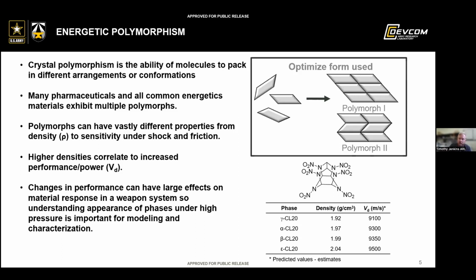So this is an example where we can use high pressure to understand how this material responds under these pressure conditions. Because the diamond anvil cell technique is such a small amount of material, it involves a very low amount of risk to the experimenter and to any kind of measurement that we would take. And because it also uses a very small amount of material, we can do this very early on in the